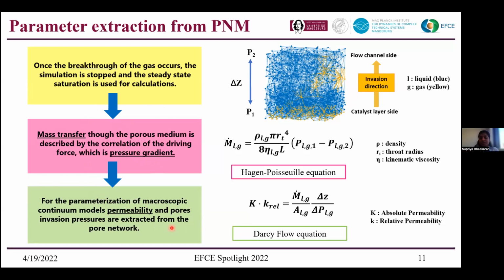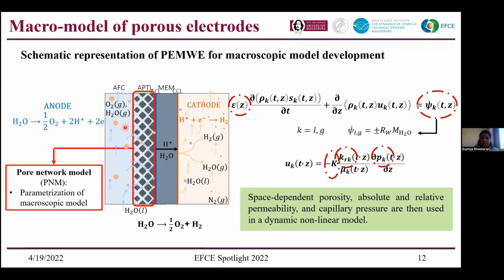Once we derive this data from the pore network, we move to the macroscopic scale. So in the macroscopic scale, again, for the anode layer, we use the continuum model equation, where we take into consideration our reaction terms, the spatial dependent porosity, the absolute permeability and relative permeability, as well as the capillary pressure for each pore into our nonlinear model. So this is under development right now, and it would be nice if we are able to get more data about the efficiency, the potential of the electrolyzer. So this is one of our scope that we are right now working on, the macroscopic model.